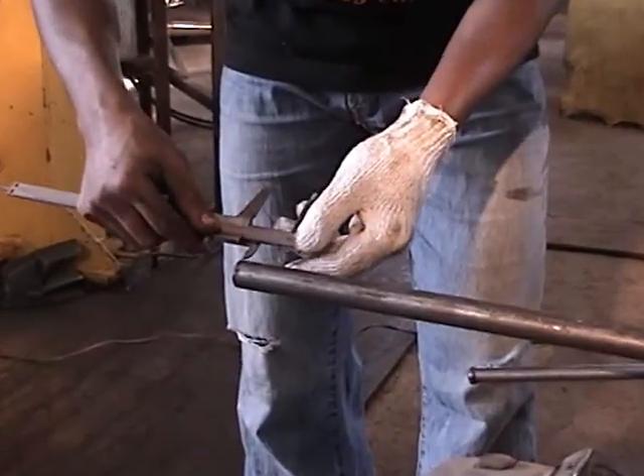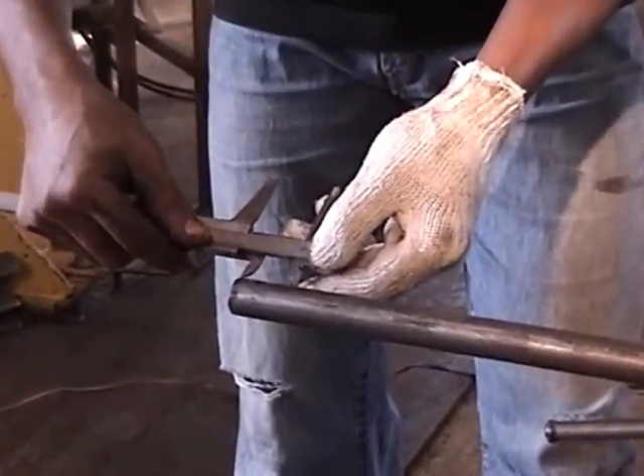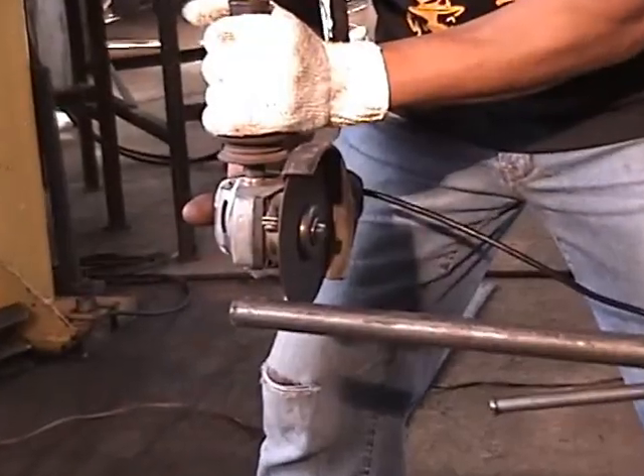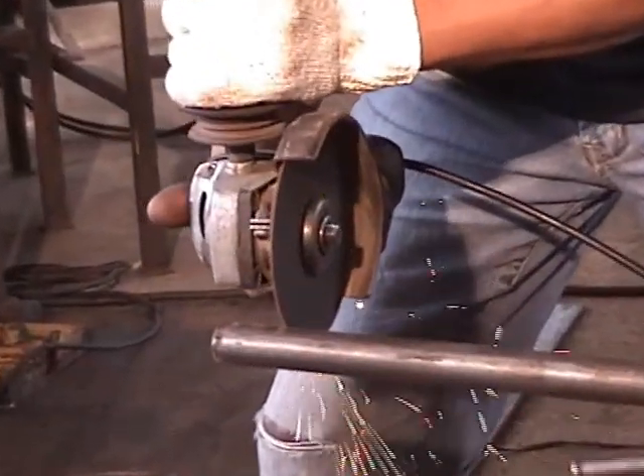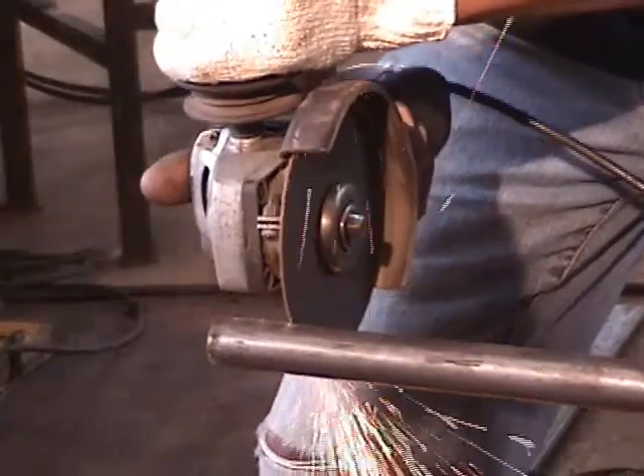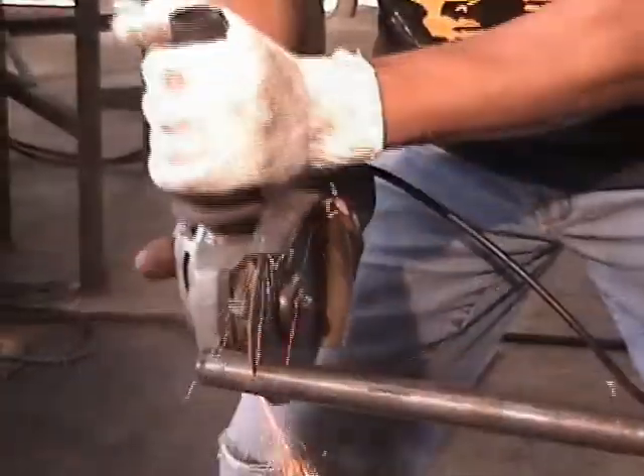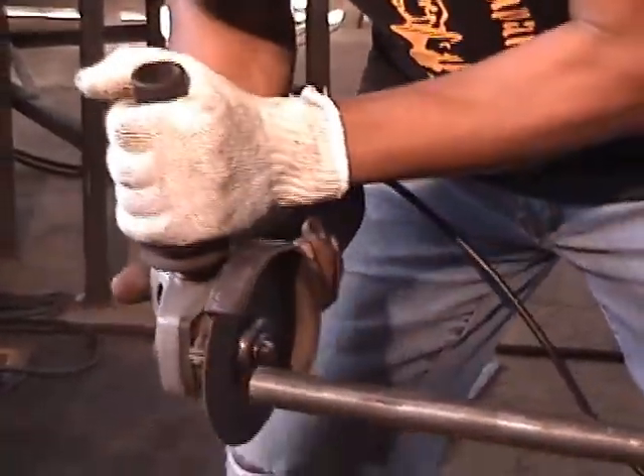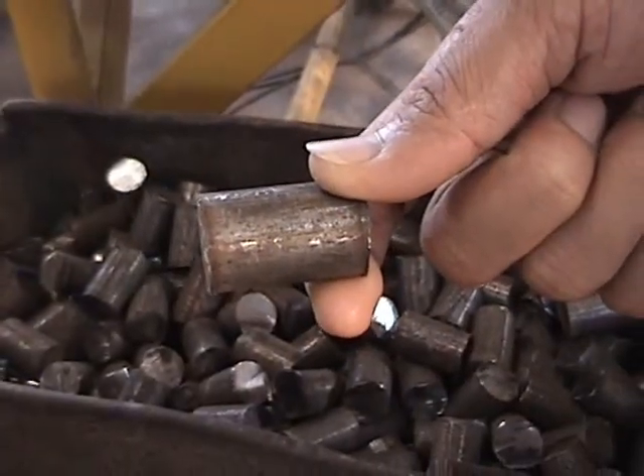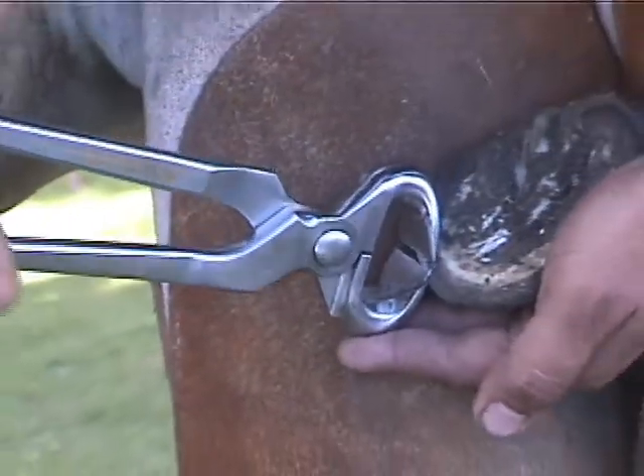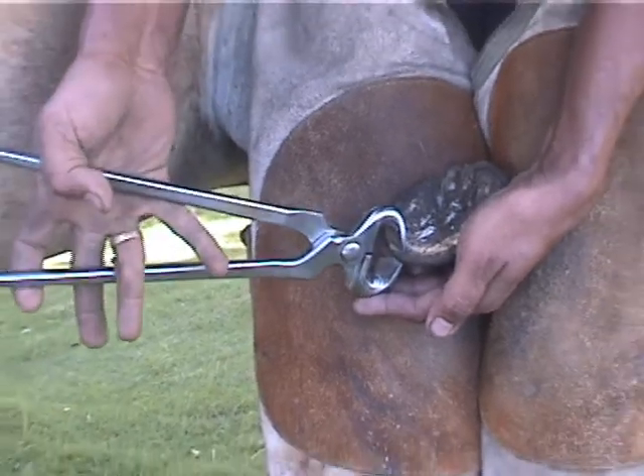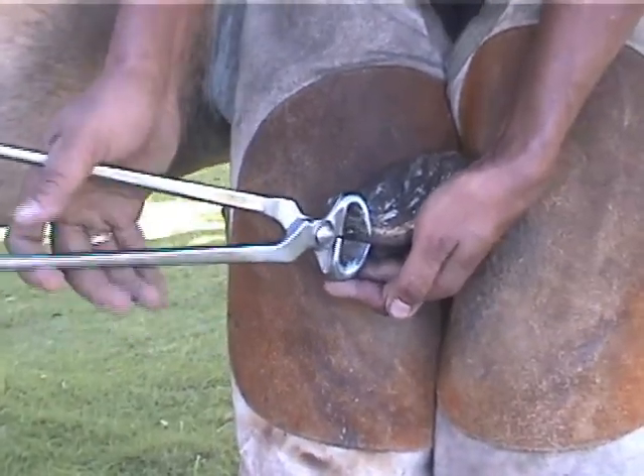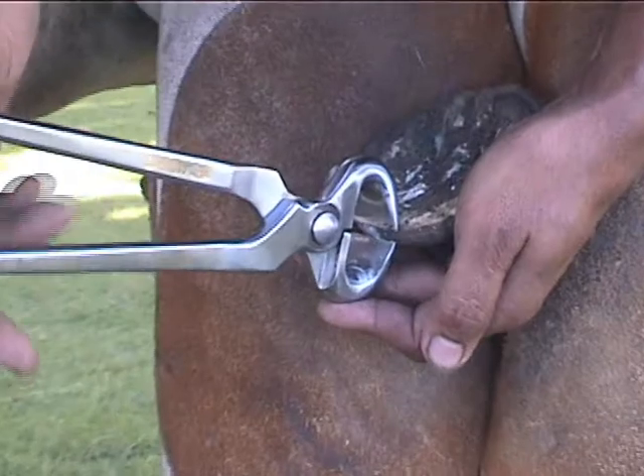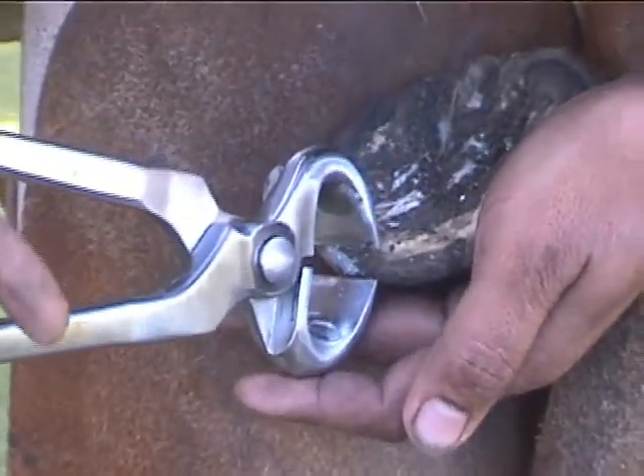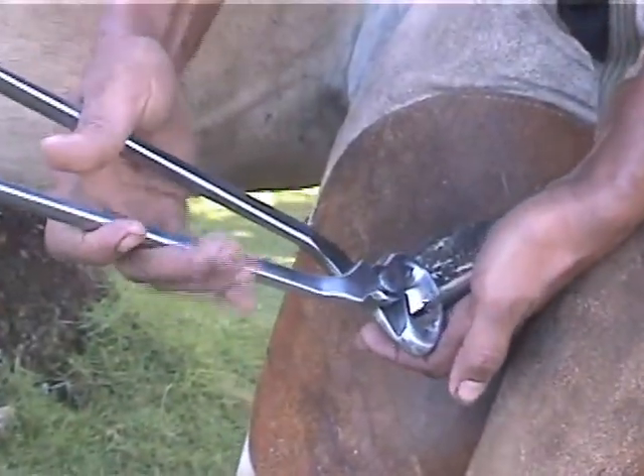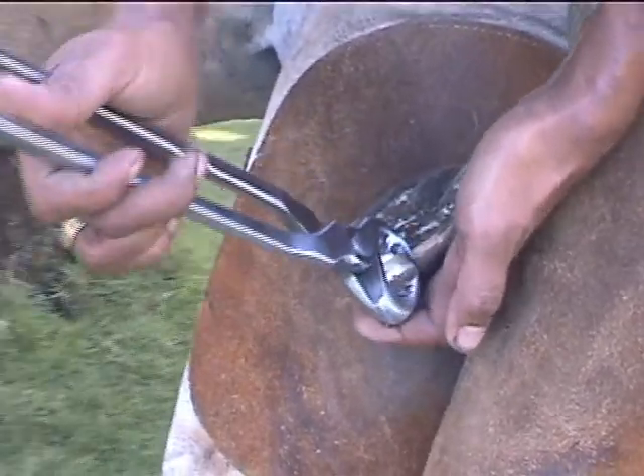First, you can see that we are cutting a small piece of steel off of a 3/4 inch diameter joint of H13 steel. We use H13 tool steel for the blades because it is the only steel that will be tough enough to do the job. Those of you who use MFC hoof nippers may have noticed that they tend to last at least half again as long as other nippers, and oftentimes twice as long. Also, the blades stay sharper much longer.